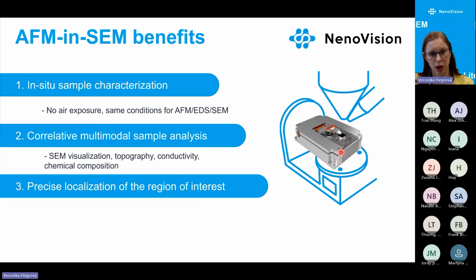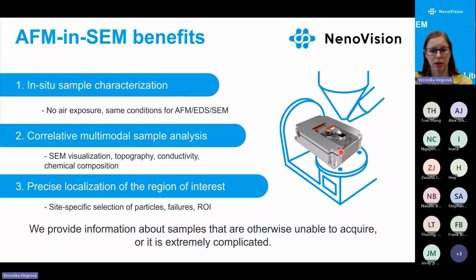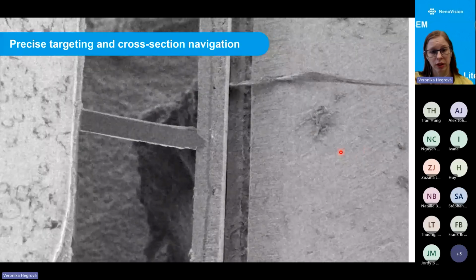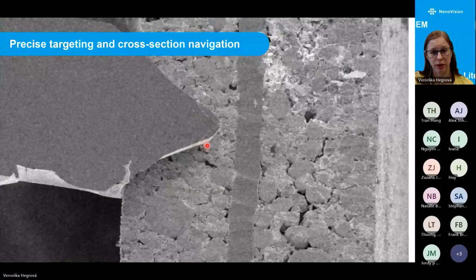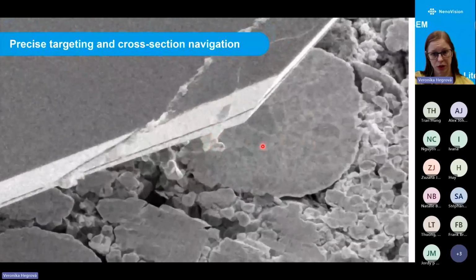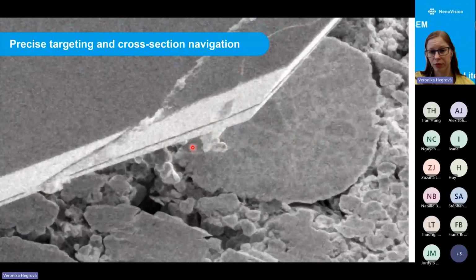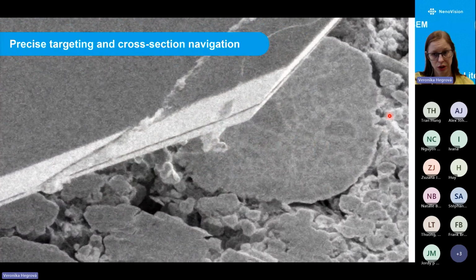And I would point out third benefit as well, precise localization to the region of interest. So we can specifically select a particle, failure, defect, basically area of interest, and start analyzing. So we are providing information about the samples that are otherwise unable to acquire, or it's extremely complicated. So you can see a precise targeting. The AFM tip cantilever is here and the sample was in the cross section, we can choose exactly the grain we'd like to analyze in the cross section.